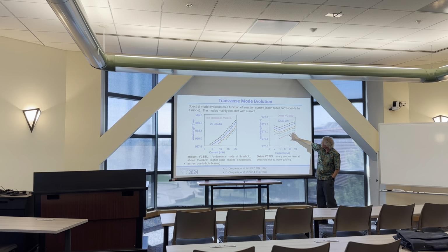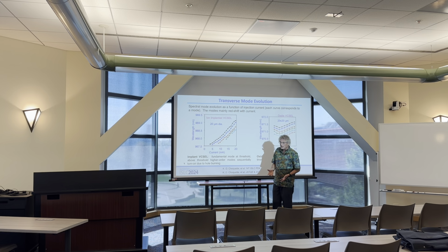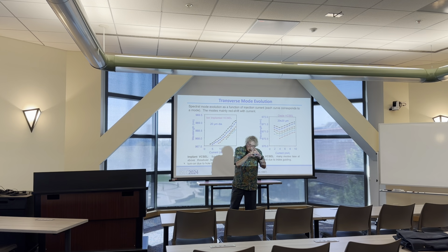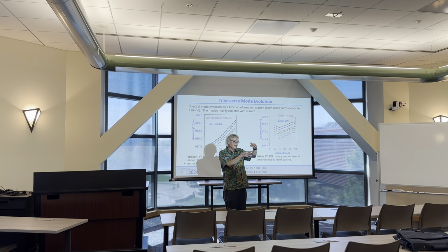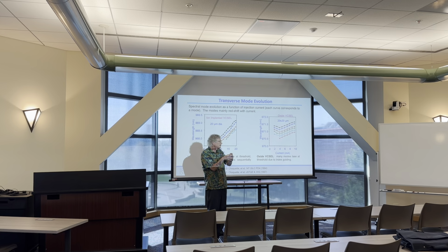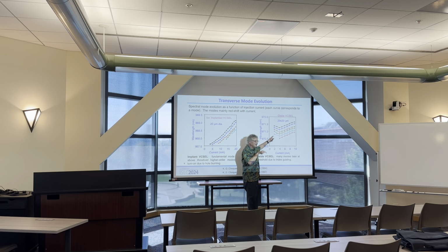The other thing you'll see is that in such structures, you actually see a blue shift in the wavelengths before you see the red shift. And this red shift is, of course, the thermal effect. What this is indicating is that the oxide is confining the current, but it's doing it so efficiently that we're not heating up. And so what you're seeing is the suppression of the index due to the current injection. And then eventually we are heating things up. Let me get back on the red shift.